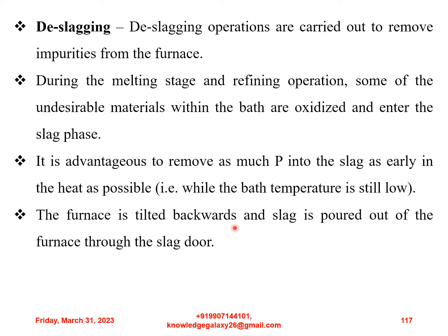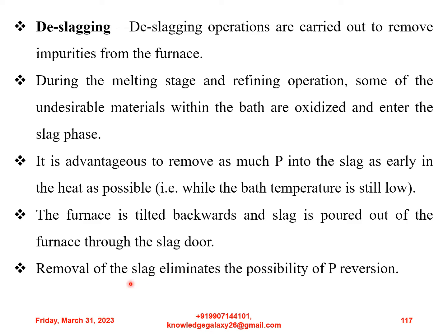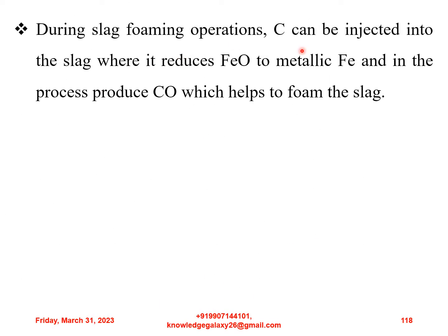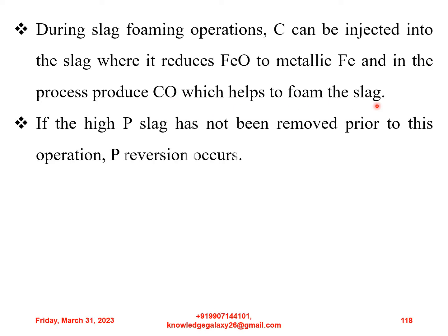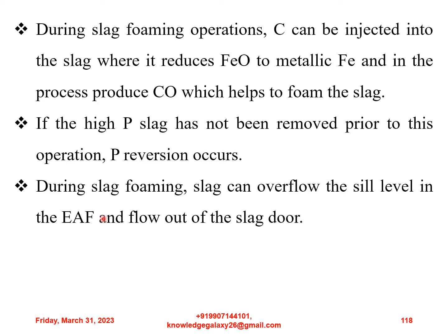The furnace is tilted backwards and slag is poured out of the furnace through the slag door. Removal of the slag eliminates the possibility of phosphorus reversion. During the slag foaming operations, carbon can be injected into the slag where it reduces FeO to metallic iron and in the process produces CO, which helps to foam the slag. If the high phosphorus slag has not been removed prior to this operation, phosphorus reversion occurs. During slag foaming, slag can overflow the sill level in the EAF and flow out of the slag door.